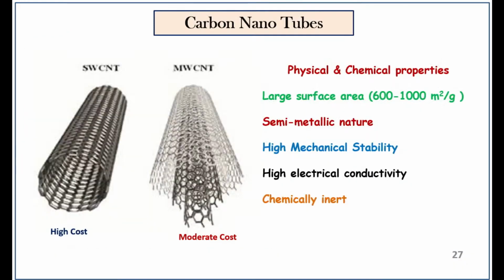So we need to improve the conductivity, because the material is a semiconductor material. So we want to deposit it over a carbon nanotube. Among carbon nanotubes, multi-wall carbon nanotube is a little bit low cost compared to single wall. It has a large surface area, semi-metallic nature, high mechanical stability and high electrical conductivity, and it's chemically inert, so we are able to use it in any conditions. So we want to deposit the MoS2 over the multi-wall carbon nanotube.